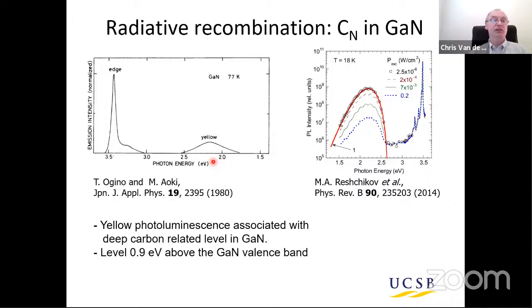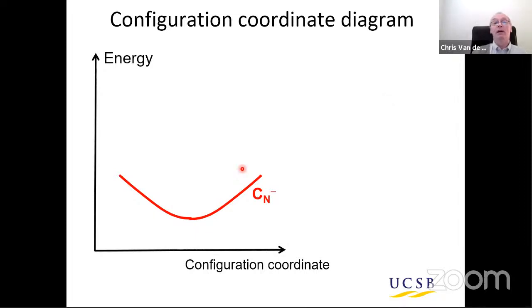And there were hints that this was related to the presence of carbon in the material. But for the longest time, basically until around 2010, there was no good explanation for what the microscopic center was that was actually causing this emission. Of course, it's tempting to think that it could be just a substitutional carbon impurity, but the information that was available about carbon seemed to conflict with giving rise to yellow luminescence.